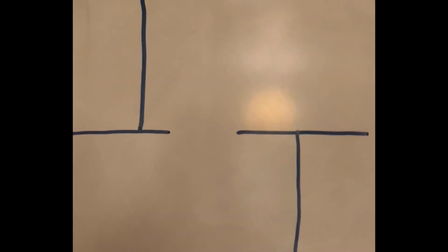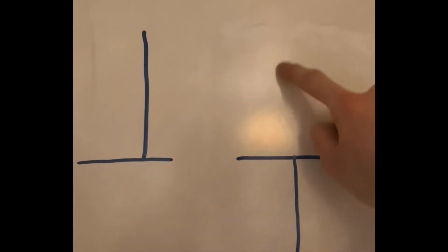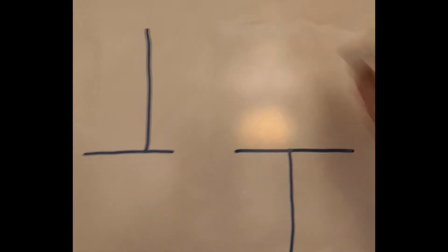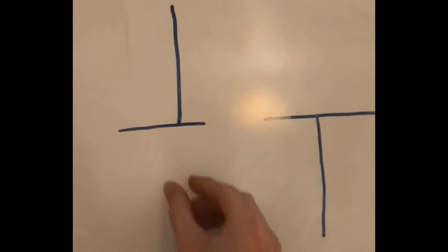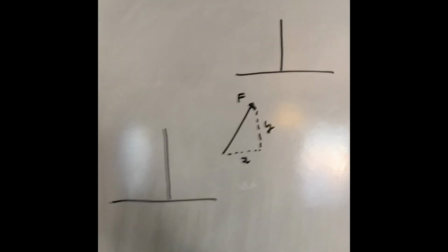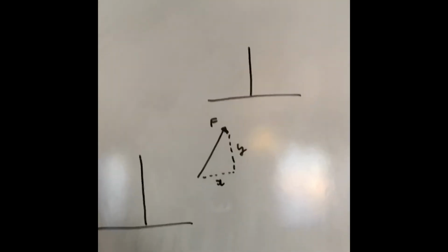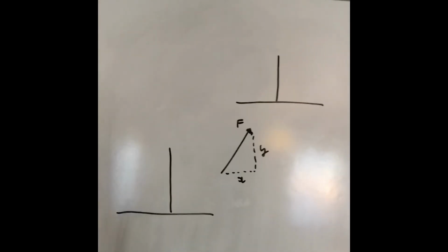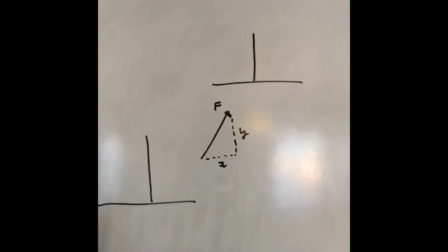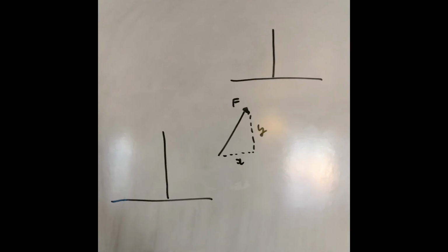They attract because of the opposite stress fields associated with them, this one being tension, compression, tension zone here, compression zone. Another scenario is when we have edge dislocations on separate planes, and these can act to attract each other in this sign convention because one will impose a force on the other.